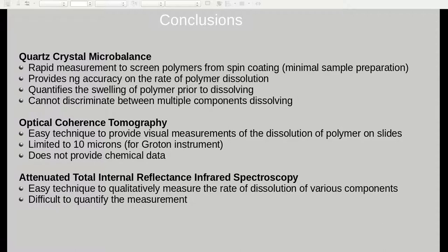This summary has discussed some new techniques to help screen formulations consisting of polymer films. In particular, we looked at QCM. QCM provides fairly accurate mass measurements of the dissolution of a polymer film. The accuracy is on the order of nanograms and is therefore sufficient for very small available masses of the polymer.